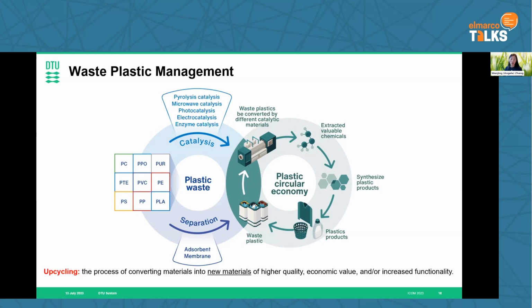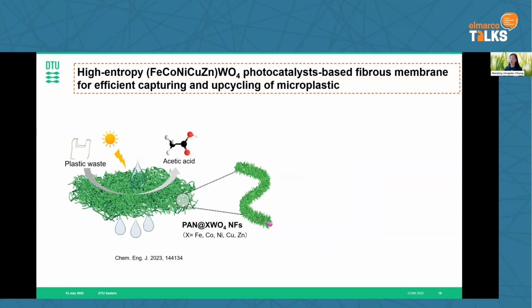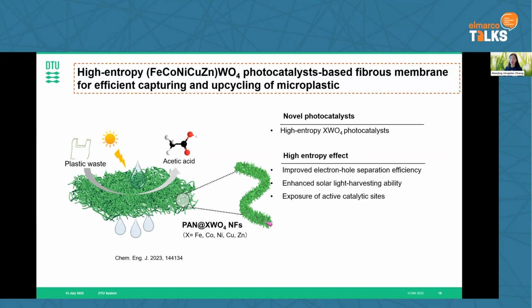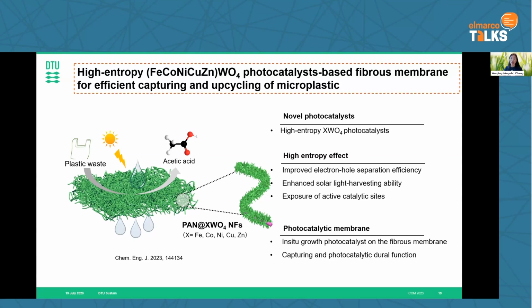To upcycle means a process of converting materials into new materials that have economic value or increased functionality. So what we did here is to put photocatalyst on top of fiber membranes. Then we can not only capture those microplastics, but also convert them into value-added compounds. So here we use photocatalyst. We synthesize our high entropy catalyst, and those catalysts have very high efficiency in terms of photoactivity, and they can absorb not only UV light, but actually solar light. So we can have solar light driven reactions as well. And we put it into the membrane structure in a way that we can capture those microplastics, and then we trigger the reaction at the same time.